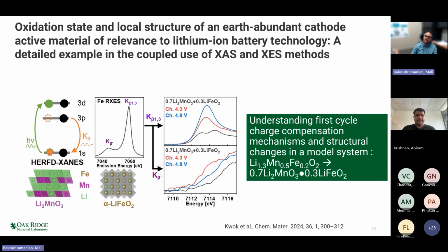So the experiment that we performed is what is called a high energy resolution fluorescence detection, where you take an electron from the 1s level and put it into a 3d level, for example, when you are at resonance, and monitor the K beta emission that comes here. You can see that the K beta has these two lines. One is called the K beta 1,3 with high intensity and a satellite line of lower intensity. These two lines come because of an exchange interaction between the 3p and 3d levels.